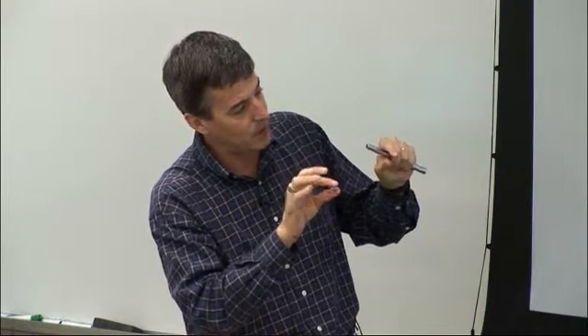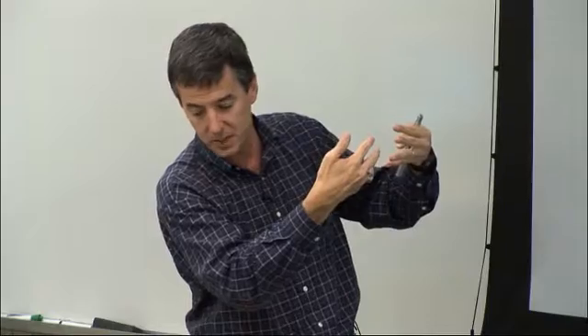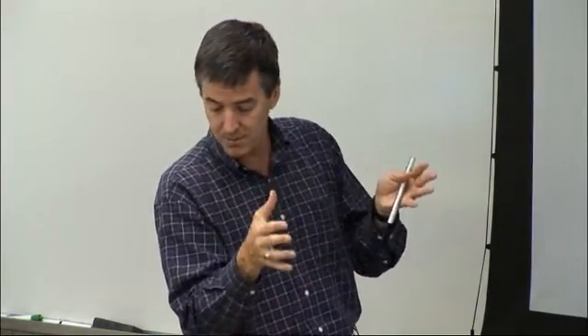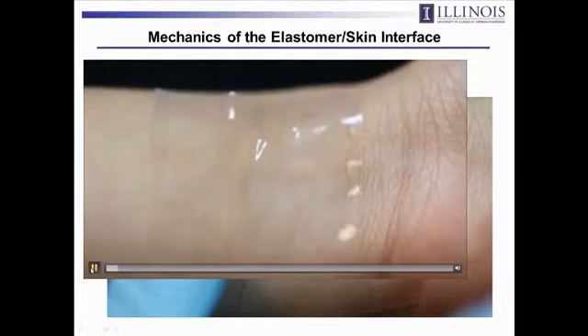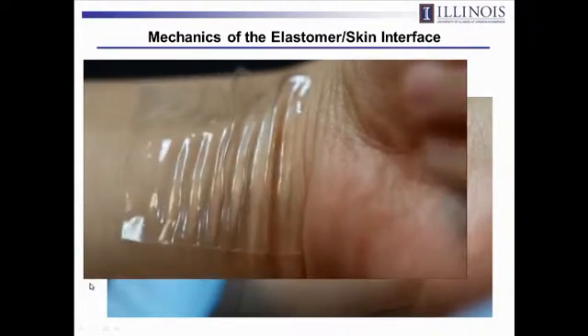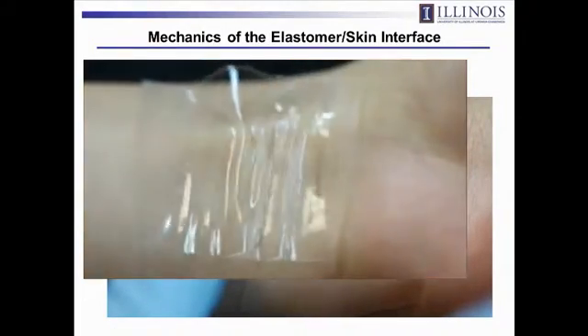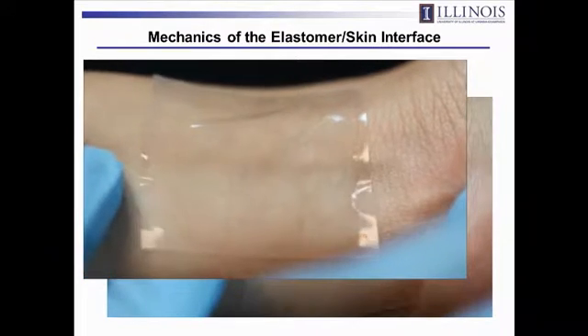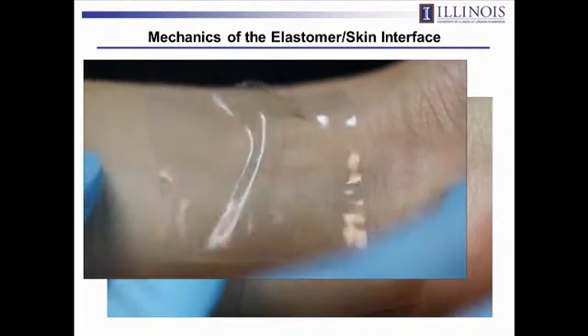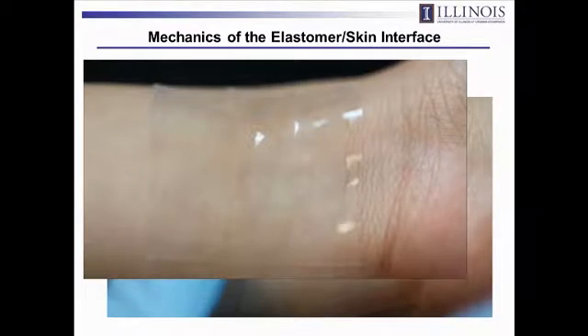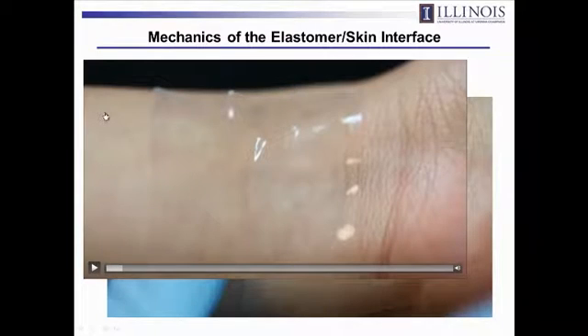So this is same chemistry in an elastomer, a silicone-based material. All we've done is we've changed the density of crosslinks between polymers in this material to change its modulus. Same thickness, same interface chemistry, just different modulus. And you can laminate it onto the skin. It's sort of near the wrist. And then you can flex your wrist and you can see what happens. No adhesive. This is just a tackiness of the material itself keeping it bonded. So here's a silicone material with a modulus of about 1 megapascal. So you flex your wrist and it delaminates. You stretch the skin. Again, it drives a delamination front that begins at the edge. Now if you do the same exact experiment now with, let me see, can I get rid of this?